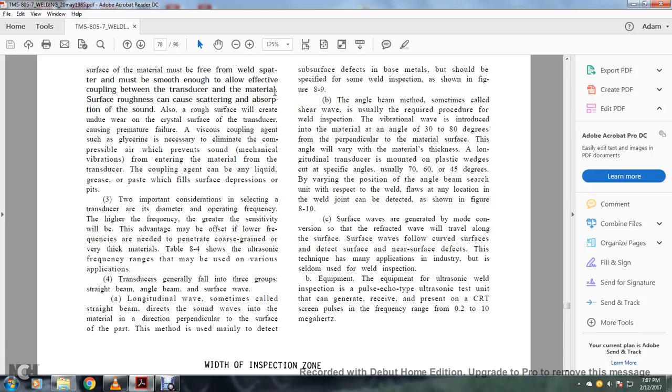B, the angle beam method, sometimes called the shear wave, is usually the required procedure for welding inspection. The vibrational wave is introduced into the material at an angle of 30 to 80 degrees from the perpendicular to the material surface. This angle will vary with material thickness. The transducer must be mounted on plastic wedges cut in specific angles, using 70, 60, and 45 degrees, varying the position of the angle beam. By searching with the unit, flaws in any location of the weld joint can be detected, as shown in figure 8.10.